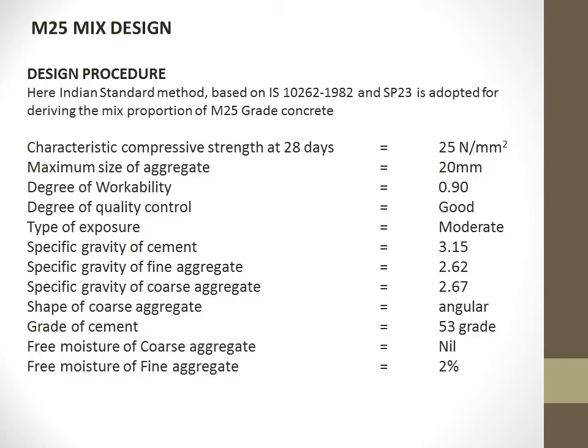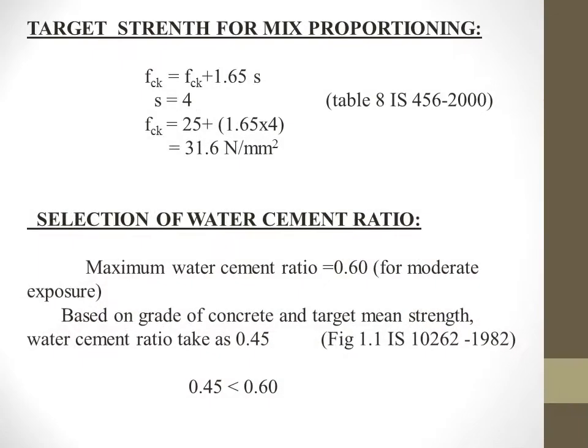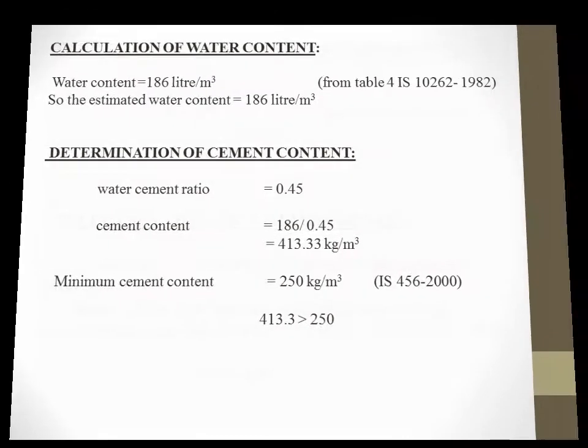The specific gravity of fine aggregate and coarse aggregate were inferred from the previous test which we had done, and the values were taken as 2.62 and 2.67 respectively. The grade of cement, as I said, is 53 grade. The target mean strength was found to be 31.6 Newton per mm square. The water cement ratio we had taken as 0.45, which is lesser than 0.6.